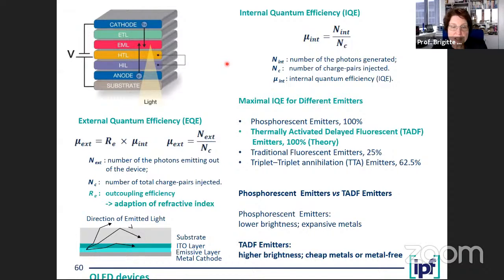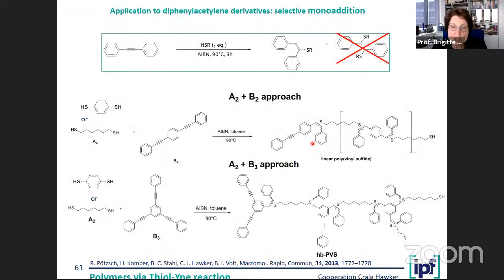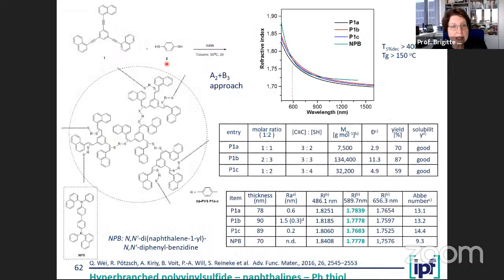And the last part, I only give you a glance. In the OLED part, you need more functional material. Here we worked on two parts. One is a material with an adapted refractive index, and the other one is the active material, which gives the fluorescence. The materials with the adapted refractive index contain a lot of aromatic rings and sulfur units, as shown here, and they are prepared by the addition reaction of thiols to triple bonds. And you see here, we also used a lot of naphthalene units and aromatic thiols, and there you can get a really high refractive index material.